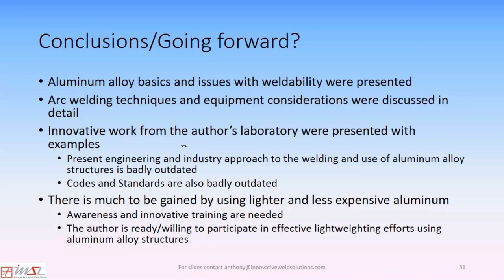for aluminum, actually. During aluminum welding, the strength in the heat affected zone will be reduced. What is the acceptable limit in the PQR? Then if the tensile strength is less than the original material. There are no guidelines on this matter. This would depend very much on the thickness combinations, on the structural application, what you're trying to do, and so on.